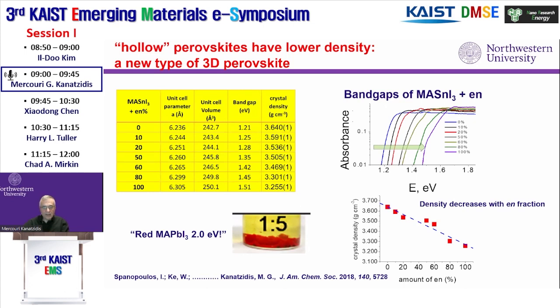We measured the density of the crystals, and it looks like it's lower. The crystals have lower density than the starting 3D material. And this happens both for tin and for lead. In fact, you can make a methylammonium lead iodide hollow perovskite that has a band gap of 2 eV rather than 1.55. And that indicated, and we verified with X-ray crystallographic refinement, that there are vacancies, lead vacancies and iodine vacancies, and that explains the low density.